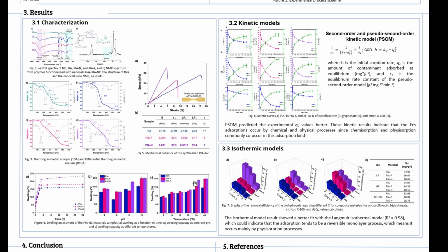The mechanical properties were determined by tensile tests according to the ASTM standard. The results suggest that the presence of nanocellulose serves as a high hydrogen bonding agent, changing the mechanical behavior of the material. Thus, the strain decreased for both biohydrogels with nanocellulose, consistent with the increment of the elastic modulus with respect to the material without nanocellulose. For example, for one of them it is almost 5 times superior, due to the materials becoming more rigid and resistant. This is consistent with the thermogravimetric analysis, where the materials with nanocellulose increase the thermal stability.